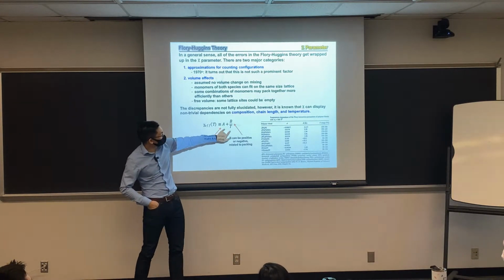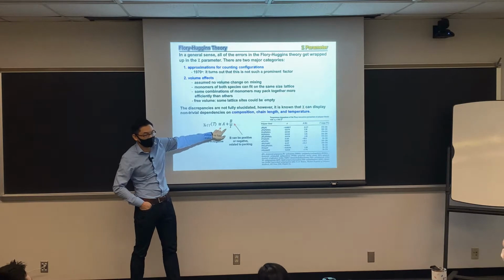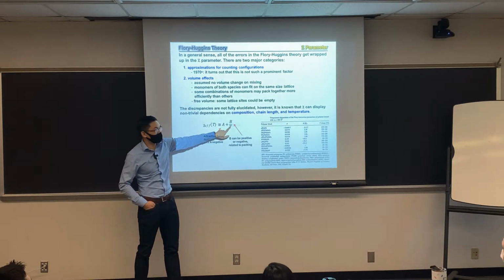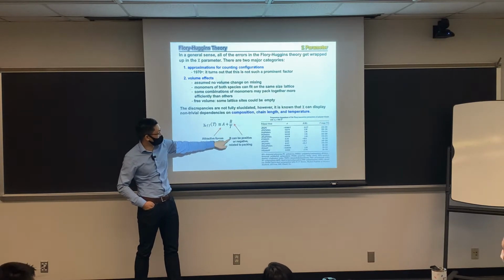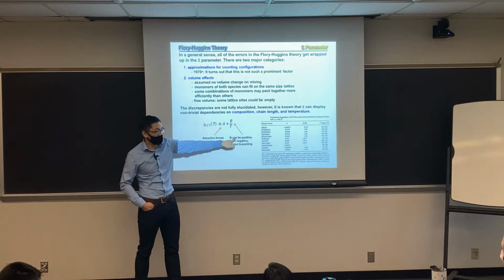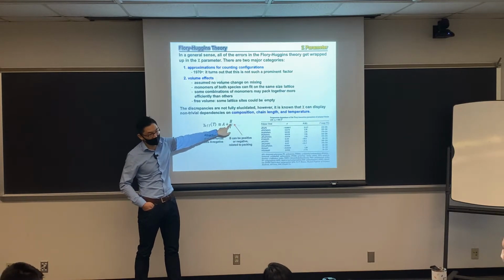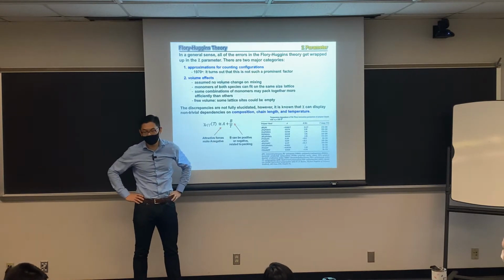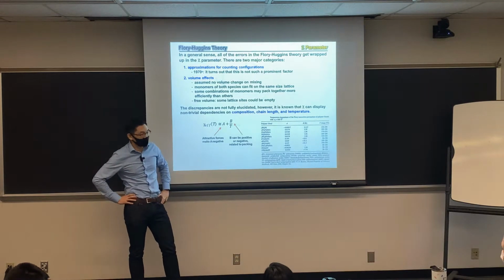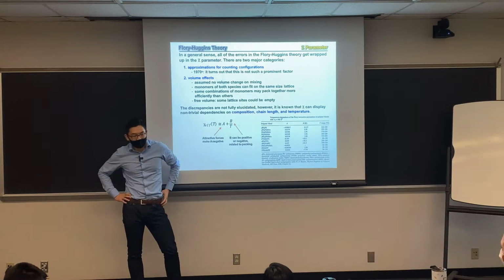So how does chi depend on temperature? If temperature rises, this T will increase. Then the value of the effective chi will depend on whether B is a positive or negative term. If B is positive, when we increase the temperature, your chi will drop. But if the B value is negative, an increase of temperature raises the chi parameter.